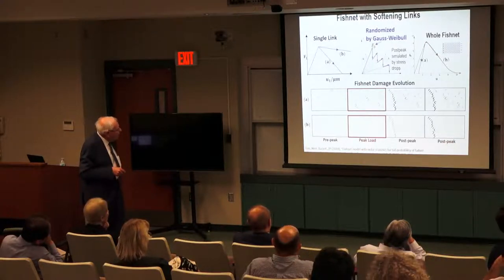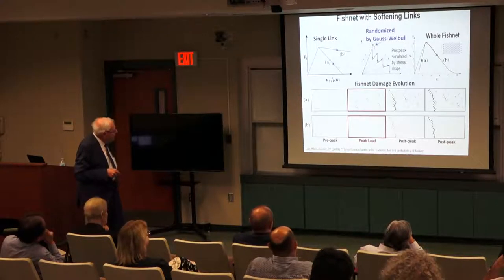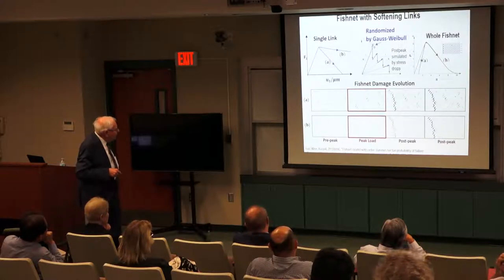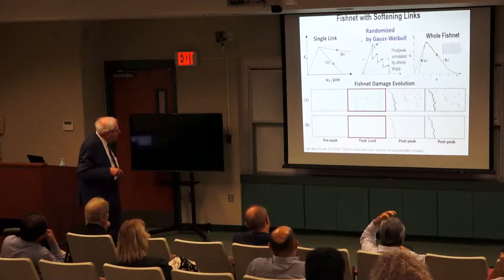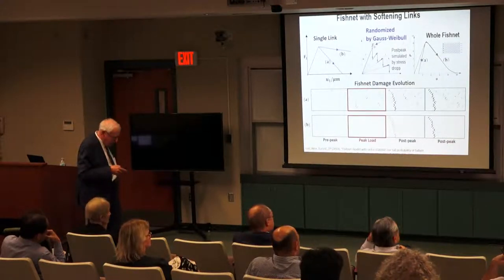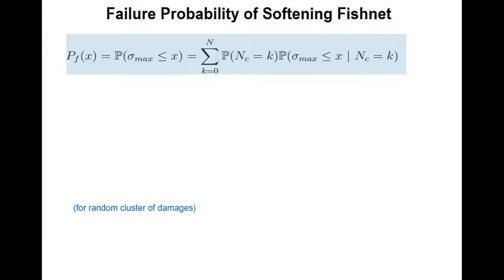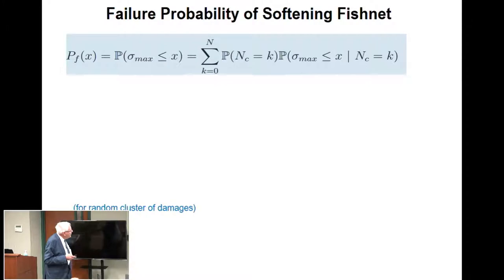So a series of jumps. And then on the whole the fishnet produces behavior like this. Depending on whether you have a vertical drop or not, it changes the behavior very much. In one case there is distributed damage, and in the other it goes suddenly. And how to approach this? The series of jumps means that we don't get failure from one jump, right? We need a number of them. We may need 20 jumps down, and then we don't need the minimum strength. We need the K-th minimum, where K can be the 3rd smallest minimum, or the 5th smallest minimum, or the 10th smallest minimum. Now this is a subject of a well-known theory, order statistics.